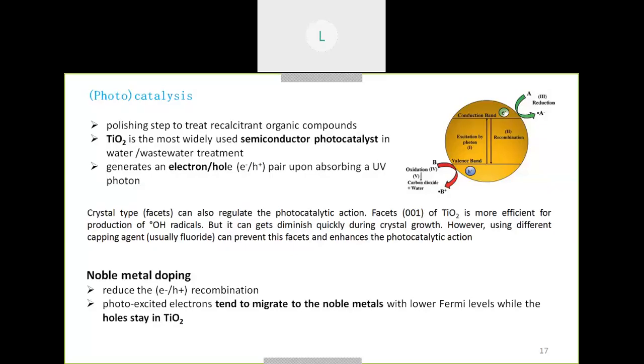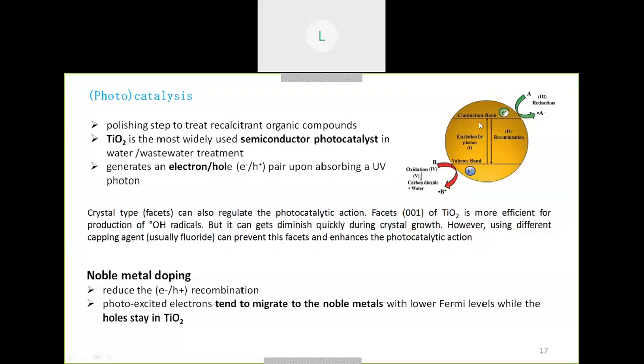You see there is a difference between the valence band and the conduction band of TiO2. When a photon with energy equal to or more than the band gap of TiO2 falls over it, the electrons jump to the conduction band, and after reacting with the oxygen in the environment, they form superoxide ions, superoxide ROS, where the superoxide can interact with your organic compounds and degrade them into lower compounds.